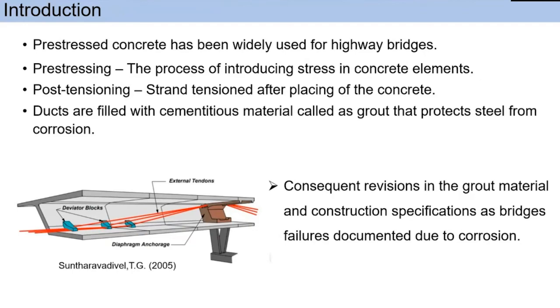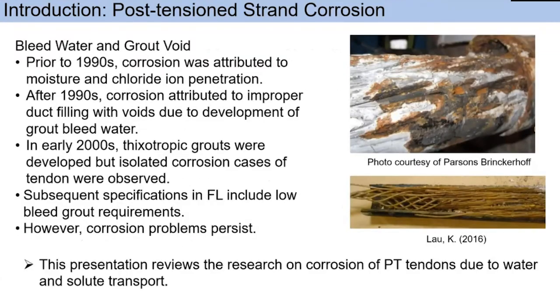There have been many corrosion failures of bridges documented in the past 30 years. Therefore, there have been many revisions in the grout material and construction specifications. Before the 1990s, corrosion was related to moisture and chloride ion, and after 1990, corrosion was attributed to improper duct filling with voids due to development of grout bleed water. In 2000, anti-bleed thixotropic grouts were developed, but still corrosion cases were observed. On the right-hand side, you can see these are the corroded tendons. The bottom one is a Ringling bridge tendon. Ringling bridge is one example of these kinds of failures.